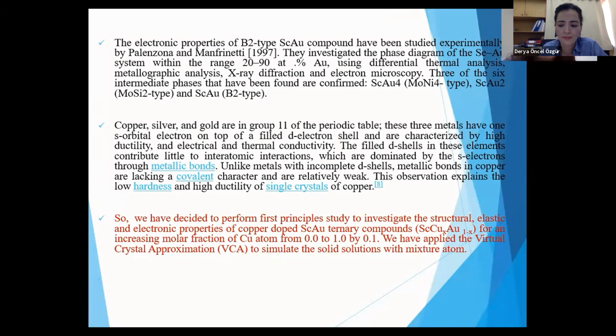metallic bonds. So we have decided to perform a first principles study to investigate the structural, elastic, and electronic properties of copper-doped scandium gold ternary compounds for an increasing molar fraction of copper atoms from 0 to 1 by 0.1. We have applied the virtual crystal approximation to simulate the solid solutions with mixed atoms.